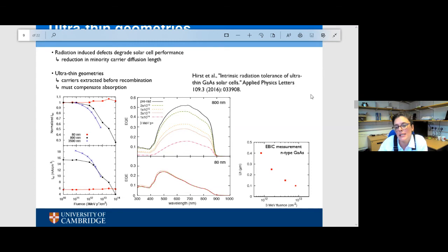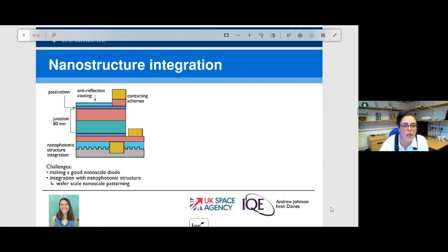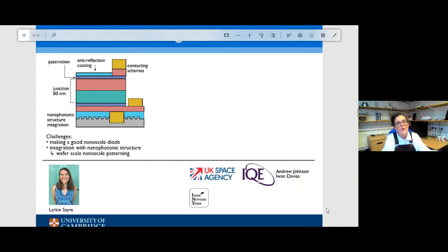And it really starts to make sense when we measure the minority carrier diffusion lengths. With this kind of radiation exposure, we end up with minority carrier diffusion lengths that are around 100 nanometers. And so we really need to be looking at devices on that kind of length scale. So the first thing to think about when we're saying devices on this length scale, less than 100 nanometers, is how are we going to make a good diode on this kind of nanoscale?